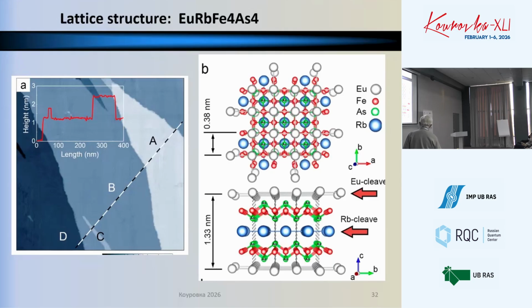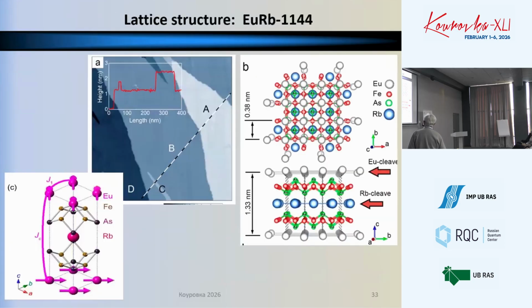So the crystal is layered. When you cleave, it can cleave either on a europium plane or a rubidium plane. The rubidium atoms are large in size, therefore it happens more often. But in any case, it doesn't cleave here, and therefore it doesn't allow the tip of the scanning tunneling microscope to have access to the superconductivity. So it impedes the measurements of the superconductivity. Okay.